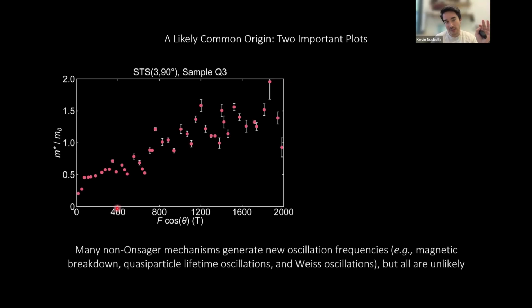And really importantly, there are many non-Onsager mechanisms in the literature that generate new frequencies that are unassociated with a new extremal Fermi surface pocket. Examples of this are magnetic breakdown: I have two neighboring pockets, and at high fields, the electron can tunnel to encircle both of those pockets and generate a new frequency. Or quasi-particle lifetime oscillations, which are virtual processes between two pockets, or Weiss oscillations, which are effectively geometric resonance signatures.